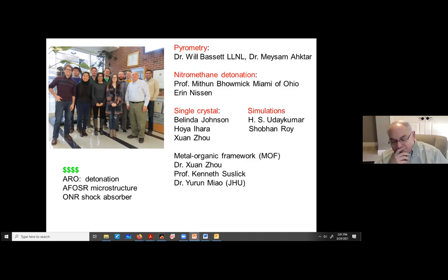And the thing you want to remember is that the amount of reaction is linearly proportional to the emissivity, which is nice. But the emissivity is a high power exponential in the temperature. So it means that errors you make in the temperature measurement become magnified greatly in the emissivity. And so by having this thing with all these channels and really high resolution, we're able to get good emissivity measurements in a short time. More questions?